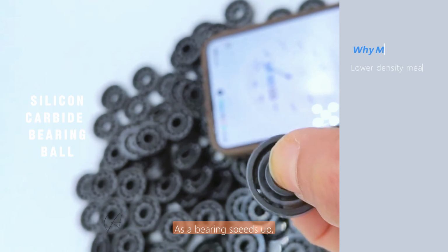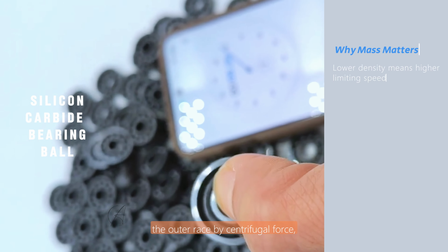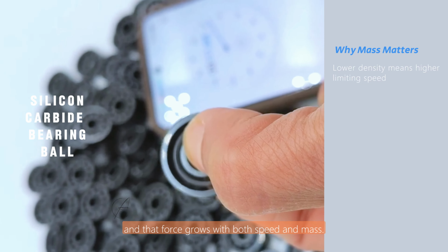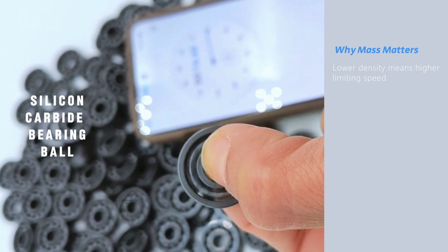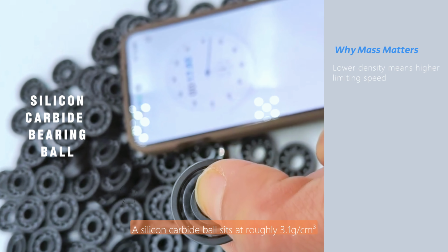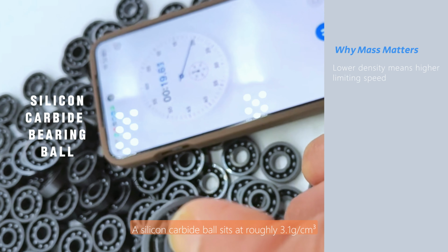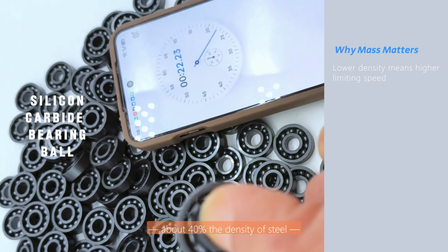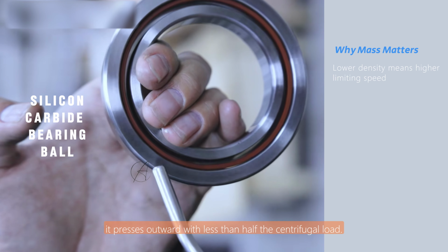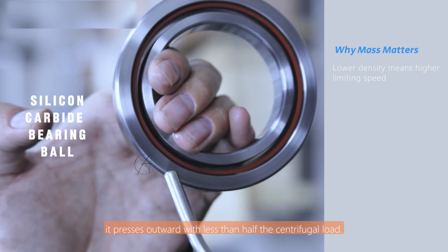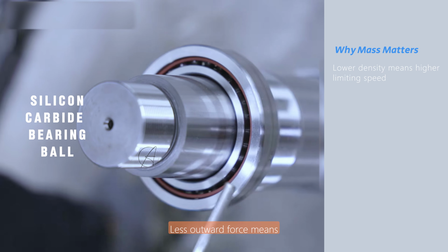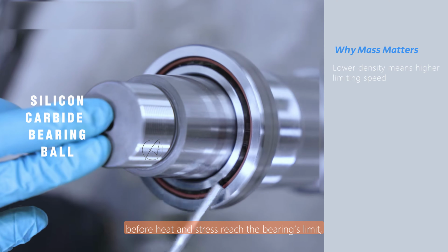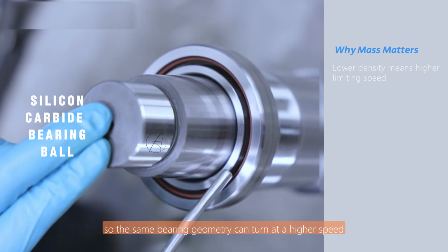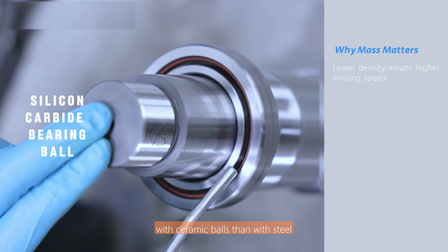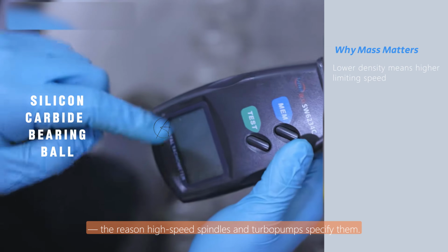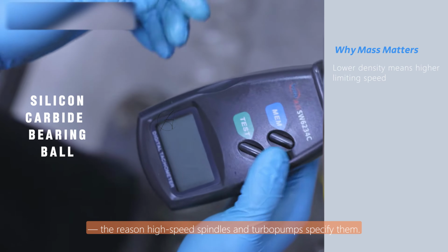As a bearing speeds up, each ball is pushed outward against the outer race by centrifugal force, and that force grows with both speed and mass. A silicon carbide ball sits at roughly 3.1 grams per cubic centimeter, about 40% the density of steel. So at the same speed it presses outward with less than half the centrifugal load. Less outward force means the ball can orbit faster before heat and stress reach the bearing's limit, so the same bearing geometry can turn at a higher speed with ceramic balls than with steel. The reason high-speed spindles and turbopumps specify them.